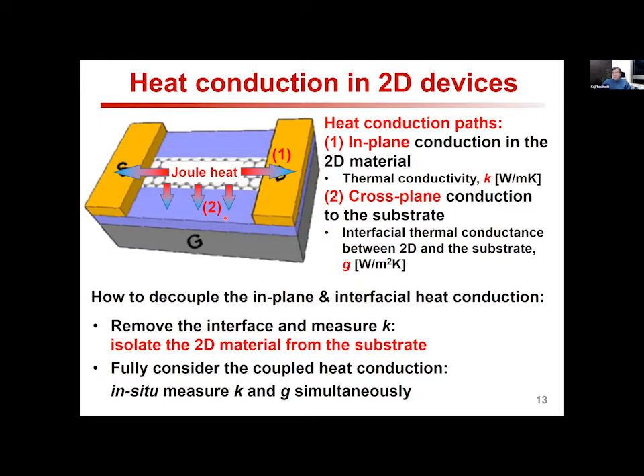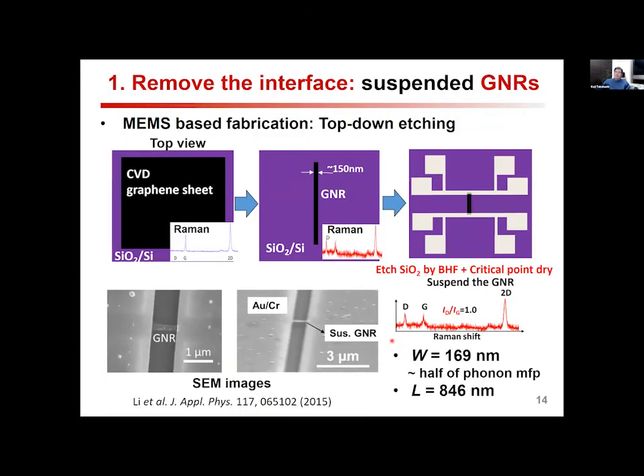Both should be considered, but at first, I'd like to talk about the in-plane conduction. In this case, we have to remove the effect of this number 2 conduction. That is, we can remove such effect by isolating the 2D material from the substrate. This is an example showing how to measure the in-plane heat conduction. By using the MEMS technique, we successfully isolate the graphene nanoribbon like this, and we could measure the thermal conductivity.